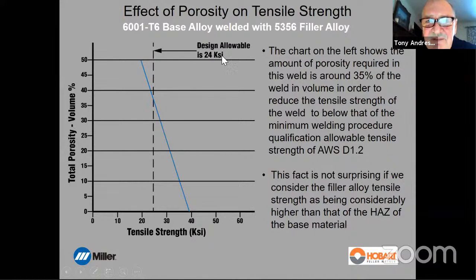Well, really, if you look at the strength of the base material and the filler alloy, minimum tensile 24, and then you've got 5356, which has got about 40 KSI. You know, you can remove a lot of this filler alloy before you drop down to that strength. So it's a bit misleading.